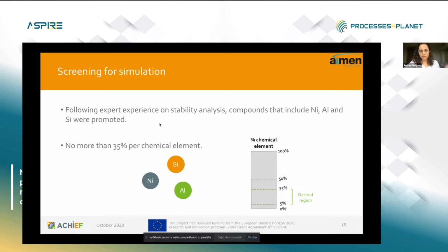So finally, following VTT's experience on stability analysis, we have promoted compounds that contain nickel, silicon, or aluminum, because these three elements are really important for the presence of the gamma prime phase, which is really important for the stability of the final compound. But always taking into account, not only for these elements, for all the elements present in the final alloy, that each element were in the desired region. So the desired region is the one which goes between 5 and 35% per chemical element. And that's everything from our side. Now it's turn to Tom. Thanks a lot.